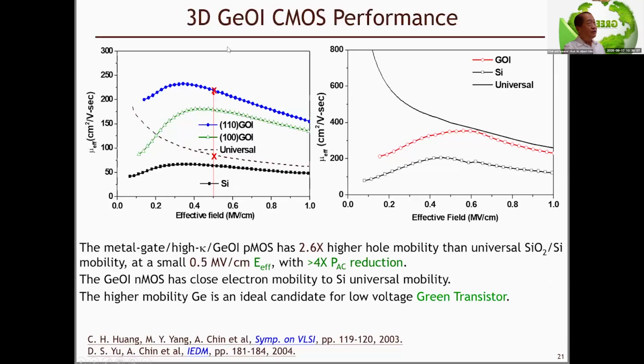So this is a 3D germanium transistor. This is the hole mobility as a function of the vertical electrical field. This transistor has 2.6 times higher hole mobility than this curve. This curve is the silicon dioxide universal mobility. So we can reduce the operation vertical effective field from 1 MV/cm to half MV/cm, which means that we can have 4 times AC power reduction or operation power reduction. The germanium CMOS is also reasonable. So the higher mobility germanium is an ideal candidate for low voltage green transistors, shown here.